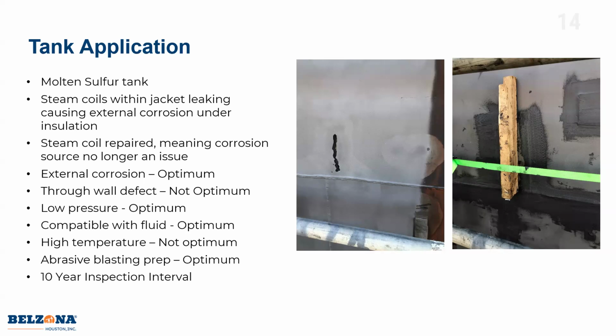So looking at this application, this is a molten sulfur tank. And the issue was not actually the molten sulfur, it was the steam coils were leaking within the jacket, which caused accelerated corrosion under insulation. So the steam coil was repaired. So the corrosion issue was no longer there as far as that steam leak. So this is an external corrosion case, and the corrosion source was fixed. But even if it were to keep leaking, we have the wrap on top of it as well, so that would stop it from corroding.